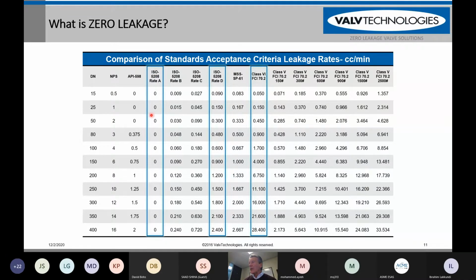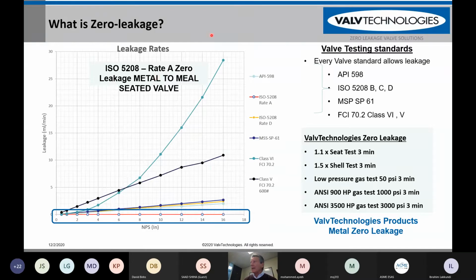The leak rate that we always use is leak rate A on our metal-to-metal seated valves, which is exactly zero leakage. Again, to show you in a graphic form, here's a number of different industry standards for when manufacturers are shipping their valves from the factory. They must meet these standards. If your standard is FCI 70.2, you can see that the leak rates on a 16-inch valve can become quite severe. ValvTechnologies leak rate is always the same. We utilize ISO 5208 as referenced by API 6D, and we utilize leak rate A.